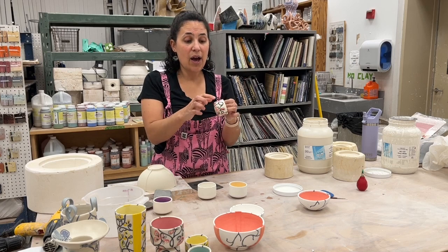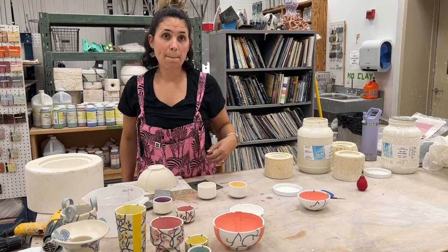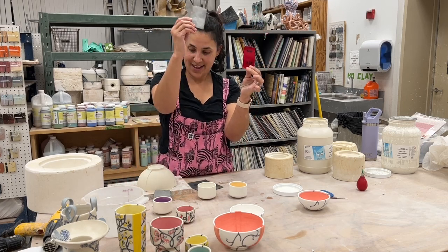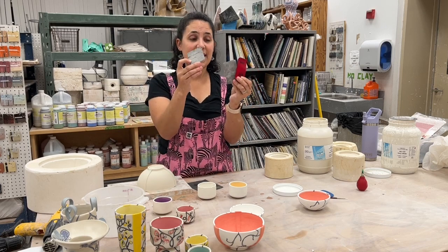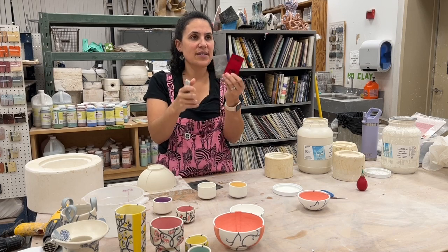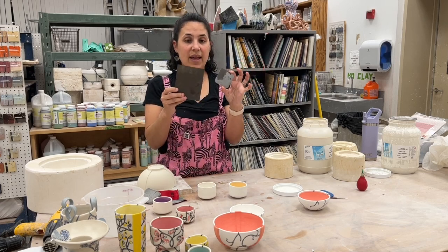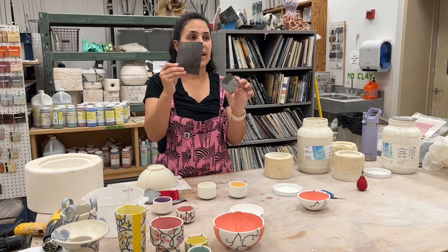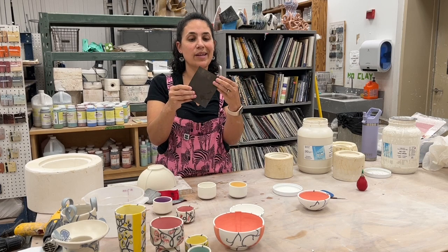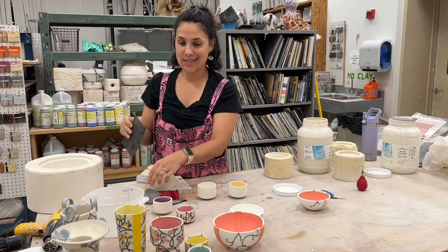The difference in texture on the final piece — you can feel on the finished pieces how smooth it is, and then there's some contrast from the decals because the decal surface is a little bit rough. For grits: I use 200, then 400 gets a lot of use — both 400 silicon carbide and 400 diamond core pads — then 600, then 800. I find I can get a similar surface with the silicon carbide sandpaper.